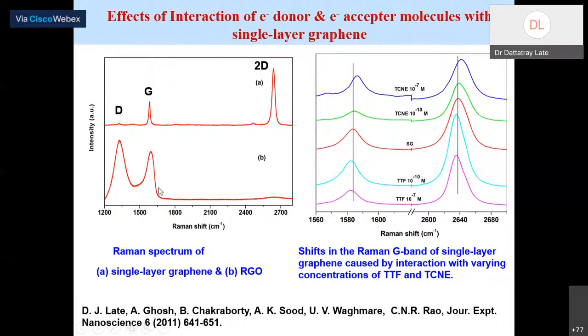And I have another one, reduced graphene oxide, right? Again, this is a monolayer, but there are a lot of defects in these graphene sheets. These are prepared by a chemical synthesis method, and I can hardly find the 2D band here, again because of the lot of defects in the sample. So what we have done here, we have prepared different concentrations of these two molecules, TCNE and TTF, and we started adding these molecules on the graphene sheet. For example, I have added TCNE with a concentration of 10 to the minus 10 molar, and I have recorded the spectra. Each time I add a different concentration of TCNE and TTF, and I monitored the Raman spectroscopy as a function of various concentrations of these two molecules.